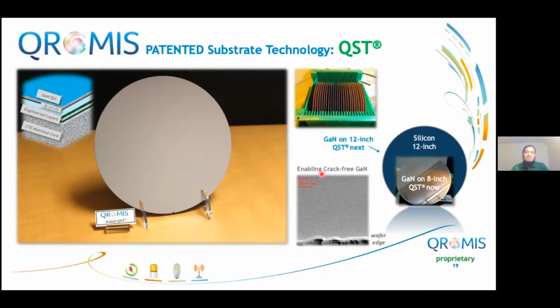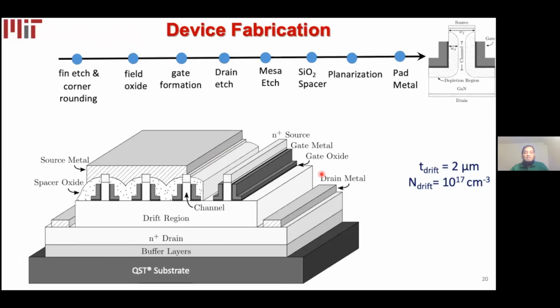Motivated by this, we started developing our own technology on this QST GaN on silicon substrate a couple of years ago. This is our typical device fabrication flow, which we have been doing in MIT.nano for many years now. Our device fabrication starts with the etching of the gallium nitride fins, and then we define field oxide to manage the electric field, and we form the gates along the sidewall of these fins. We etch the drain and mesa, and finally we do a planarization, silicon dioxide spacer, and pad metallization. I'll explain the important steps in the next few slides.